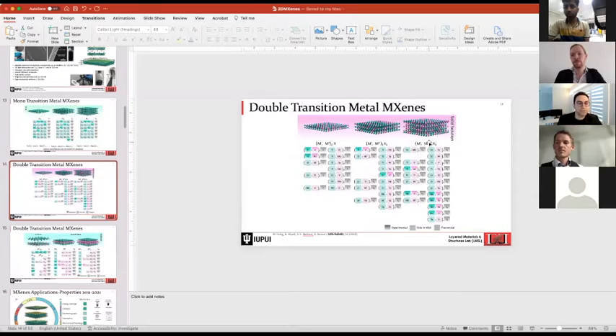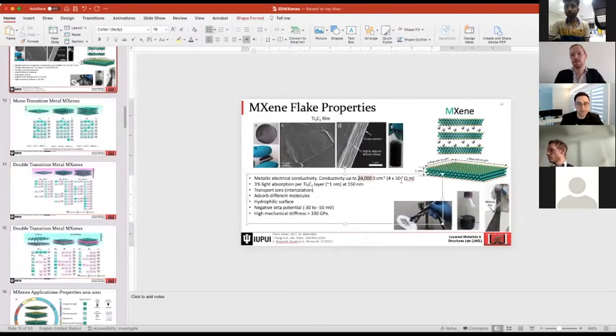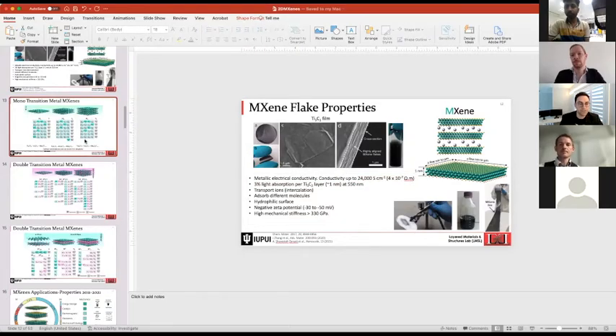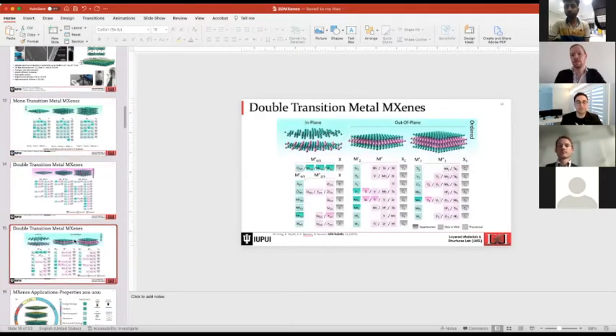So we can tune the electronic properties by playing with the composition, because when we say MXene is highly electrically conductive at this impressive number, this is only for Ti3C2. And we have right now about 40 different compositions that I have in these slides that we can synthesize. And that leads to modification of the electronic structure and the electrical properties to become more resistant.